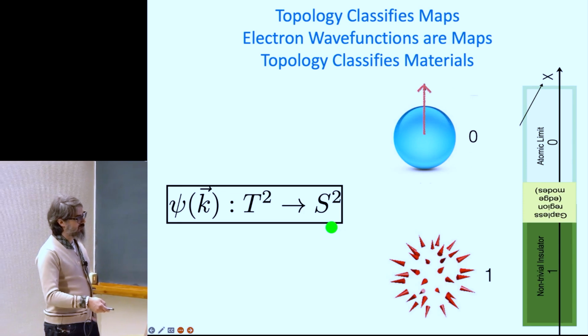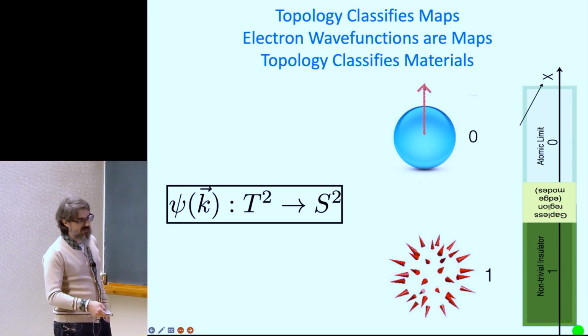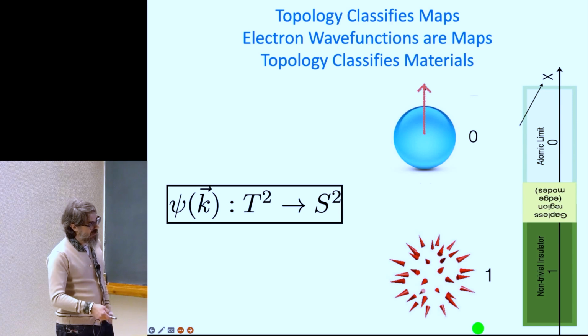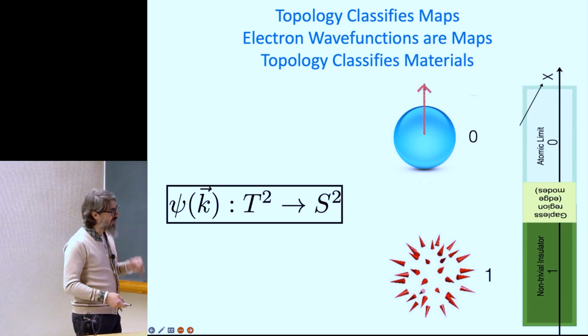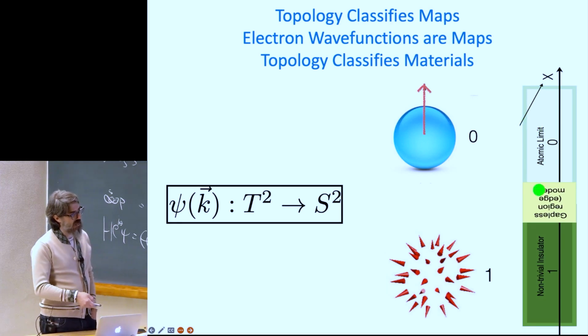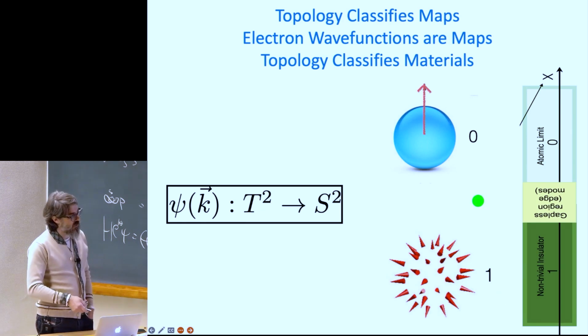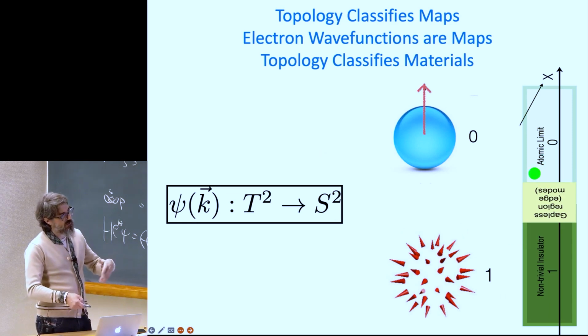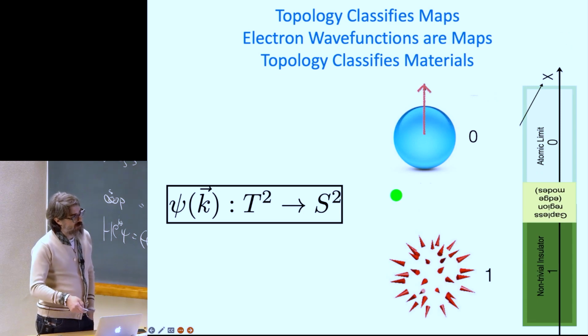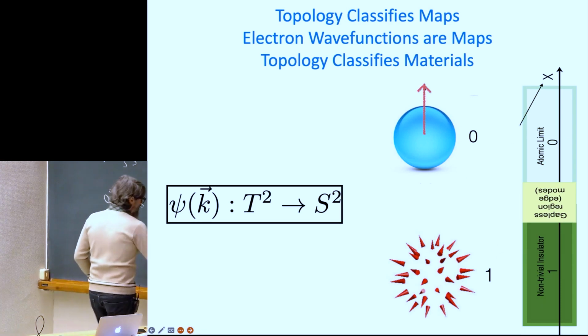So that gives you a physical principle that if I have a material like the silicon before, which actually is described by such an integer which is 0, and some other material described by an integer which is 1, then what I would necessarily have, as I would take the parameters of this material whose wave function covers this space once or twice or non-zero times, and I would try to tweak the parameters to go towards this material which covers it 0, then I would invariably have to have, if these materials are insulators, i.e. if there's no electrons at the Fermi level in this material or in this material, so there's no electrons at the Fermi level, it's kind of like that silicon that I was showing you before.